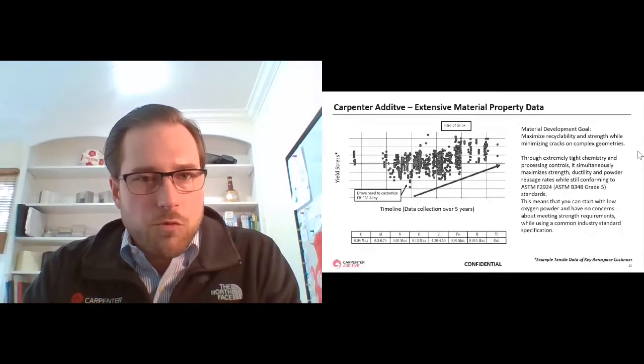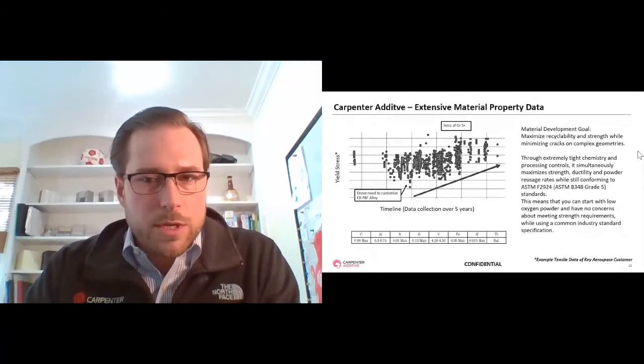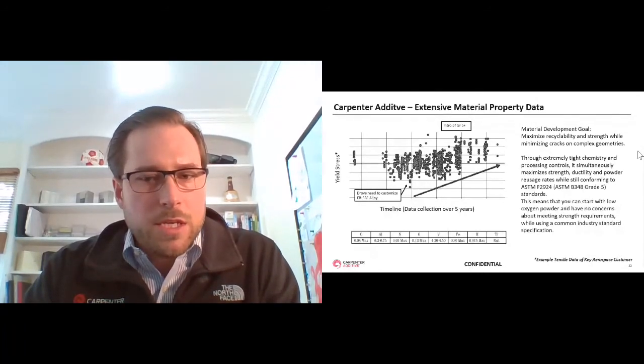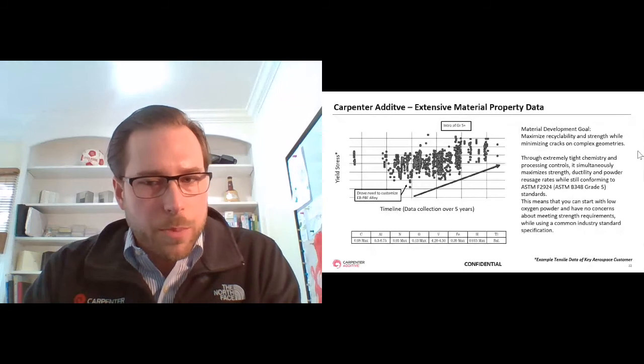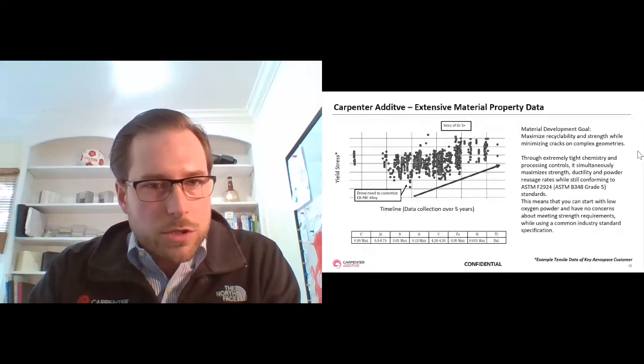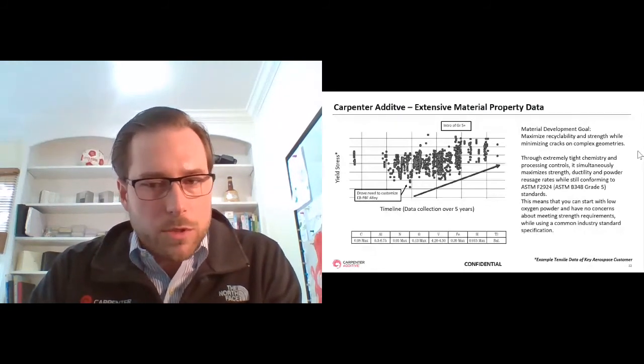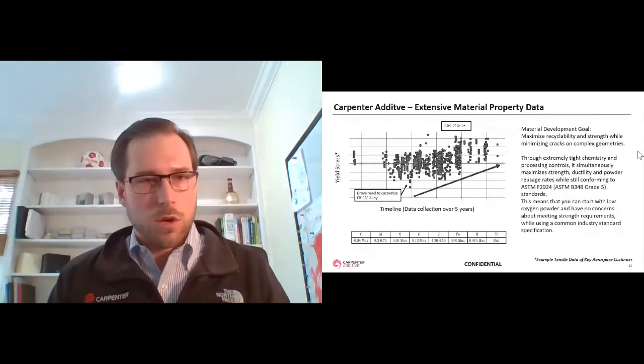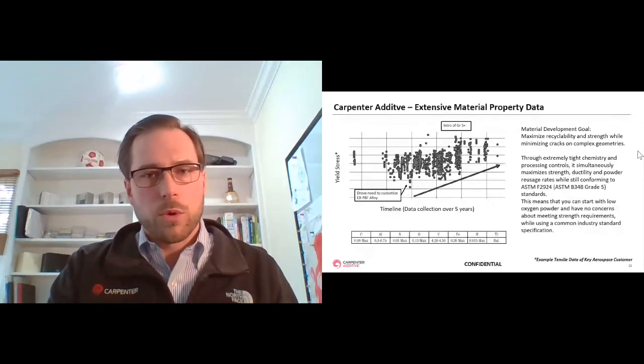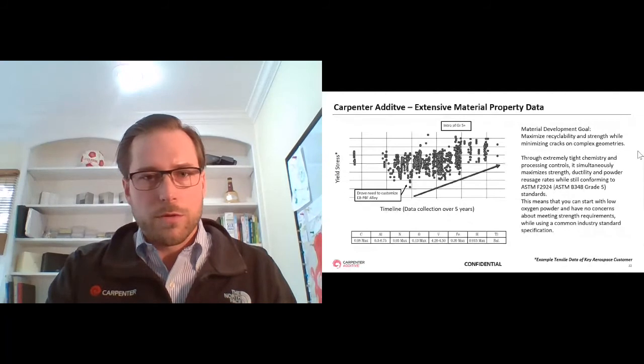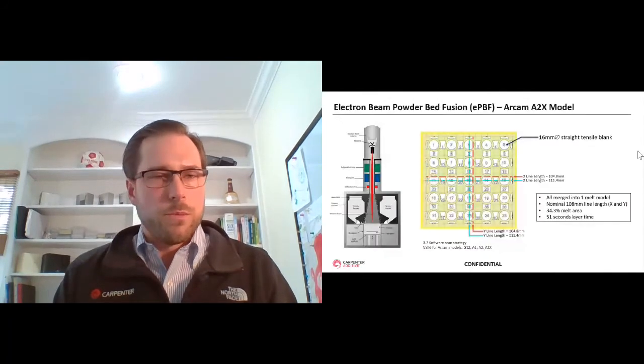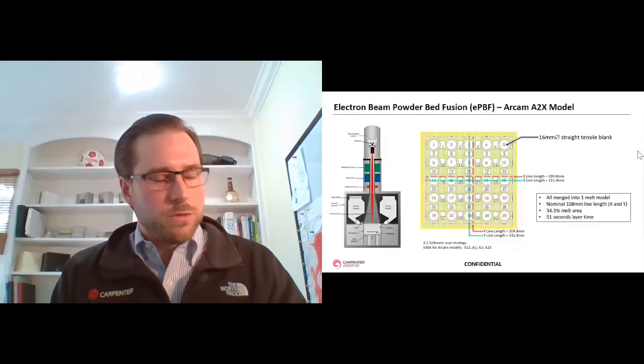So this is a really, really tight chemistry. And it means that you can start with a lower oxygen powder and not have concerns about meeting the strength requirements. So therefore you get these longer recycles. And so what I wanted to show you was a bit of data from electron beam powder fusion.